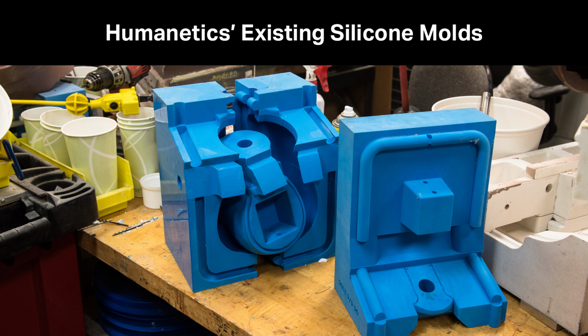All right, so you talked a little bit about silicone molds. Can you tell me a little bit about that process? The way we currently would make silicone molds is we would use our powder printer, and we would design the mold and basically print the inverse of the mold out of the powder printer. We would then mix the silicone, pour it in, and then break the powder away, and you're left with the silicone mold. The silicone molds we mainly use for thermoset parts. They have to go into the oven. They have to be heated at around 220 degrees, and some of them have to be able to withstand that temperature up to 36 hours because the parts that are poured have to post-cure in the mold because of the shape and the thickness of the parts.